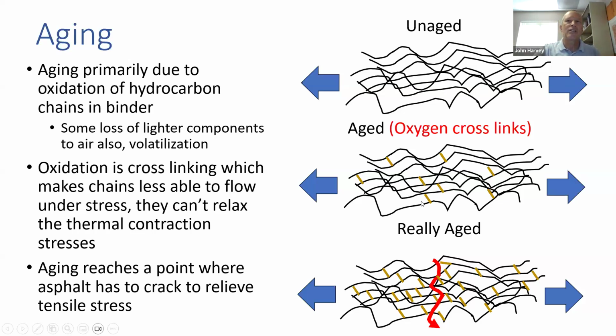As aging continues, those crosslinks become more and more, and what they do is they make it so that the hydrocarbons can't slide past each other. So what that does is it makes the asphalt stiffer, and it makes it so that the asphalt can't relax those tensile stresses that come when the asphalt gets cold. Once you have enough of those and we get a contraction, eventually that tensile stress will get higher than the strength, and we will get a crack that starts at the top and then propagates down to the bottom.